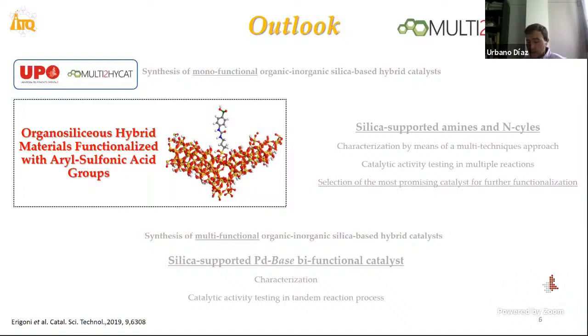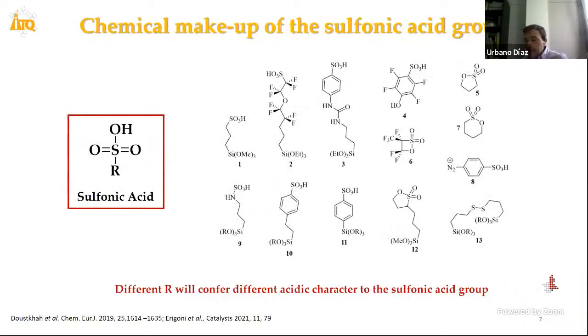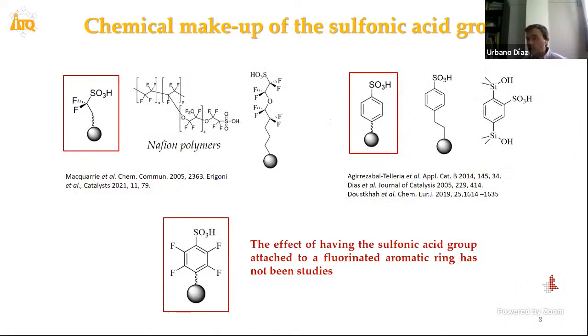The first example I can briefly talk about is the organosiliceous hybrid materials functionalized with aryl sulfonic acid groups. This work was performed mostly in collaboration with the Università del Piemonte Orientale. It's important to remember that the acidic character of sulfonic groups depends strongly on the organic groups linked close to these sulfonic groups, organic groups that are then useful to link these acidic functions in the framework of the silicon matrix. The character of this linker close to the sulfonic groups is important to determine the acidic character of this function.